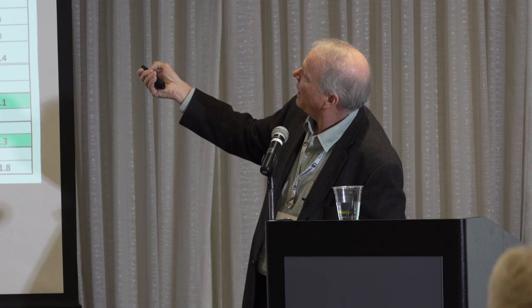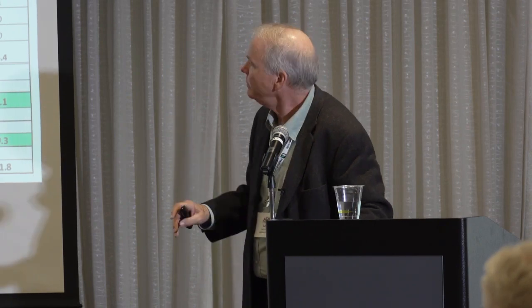If instead I use the Bellingham, that blended cement, which I talked about, that has both fly ash in it and a little bit of limestone, and I use the PLC from there. And oh, by the way, I forgot to tell you, all of these mixes have a little bit of SCM in them. They all have a little bit of fly ash, because that's what was in the average. They've got 4.6 pounds of fly ash. Did I get it right? Oh no, 14.7 pounds. Add these all up.